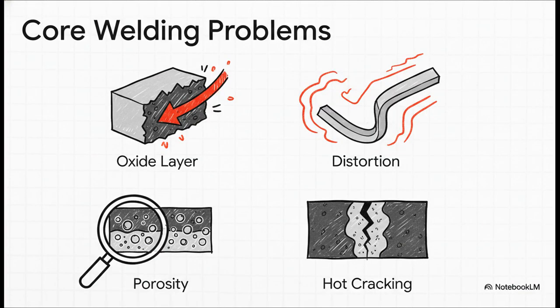First off, aluminum's got this tough, invisible oxide layer on the outside. That layer melts at a much, much higher temperature than the actual metal inside. Think of it like trying to melt an ice cube that's trapped inside a ceramic box. The metal also just sucks heat away like a sponge, which causes it to warp and distort all over the place. And on top of all that, it loves to trap gas bubbles and then crack apart as it cools down. It's a real mess.